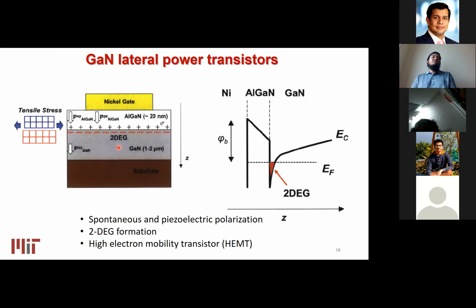Both of these materials are piezoelectric, and they have a different lattice constant. So when we grow a thin film on a thick gallium nitride, a tensile stress forms at the interface. Because of this tensile stress, there is a built-in piezoelectricity, and there is also spontaneous polarization because of their crystalline nature. So at the interface, we form a two-dimensional electron gas, a very high concentration of mobile carriers, which makes these devices really unique.